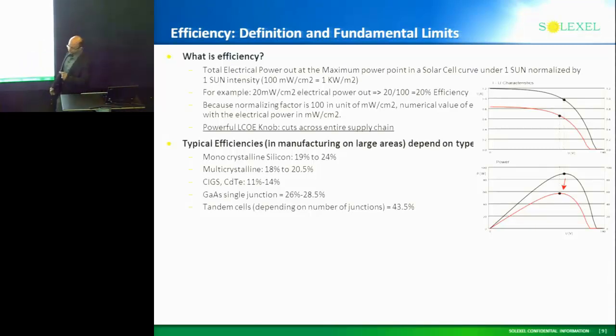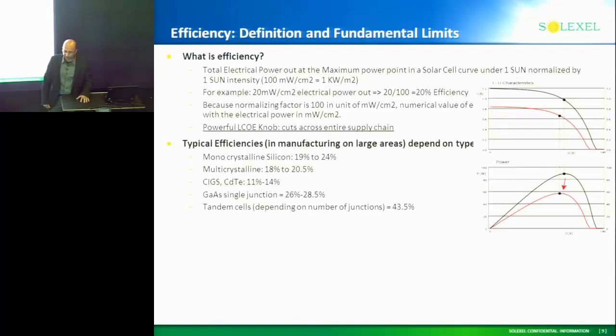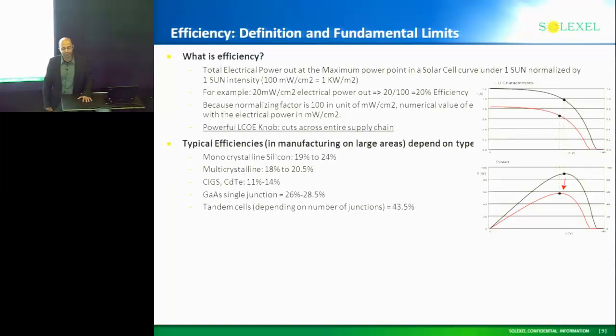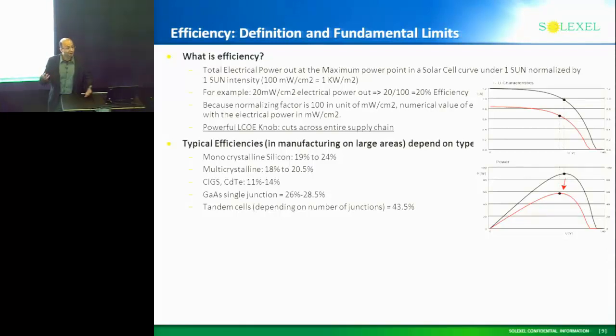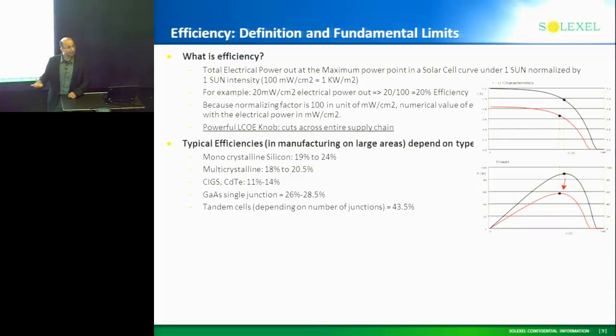What I was referring to when talking about area is that there are lots of reports. For example, the highest efficiency cell in the world for silicon is 25.5%, from UNSW in Australia. But the area is very small. It is on an architecture not considered a high-efficiency architecture in a large-area sense. If you were to extend that and say it has the highest efficiency in the world so I should make all cells from that architecture, you'd probably get burned. That architecture in practice is only 20% at large areas.